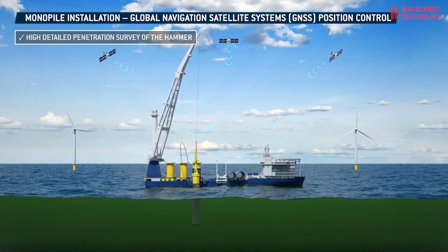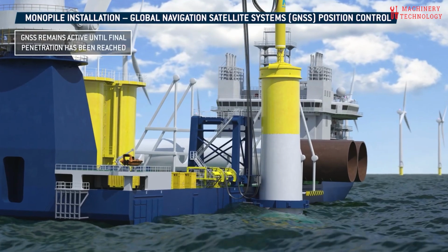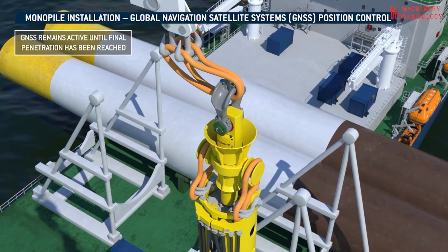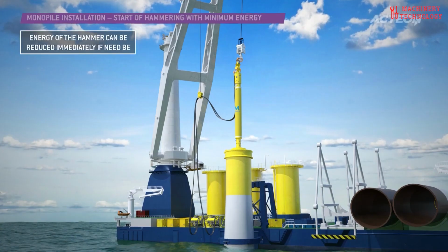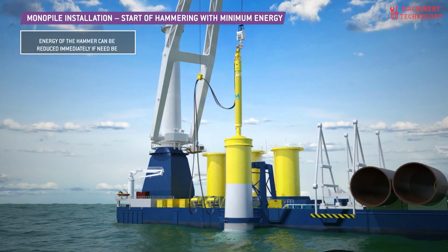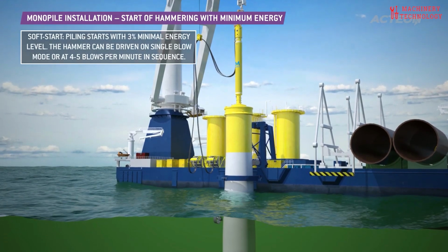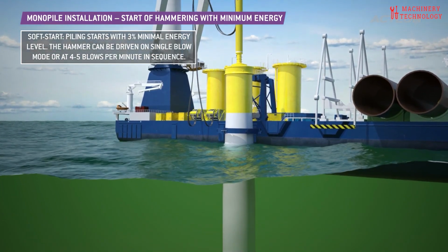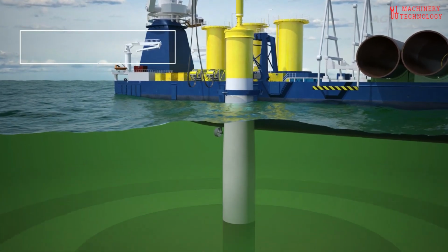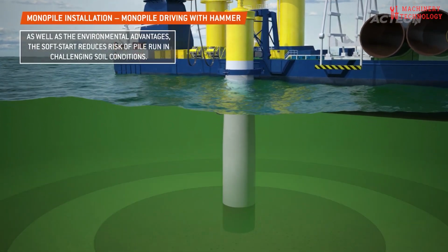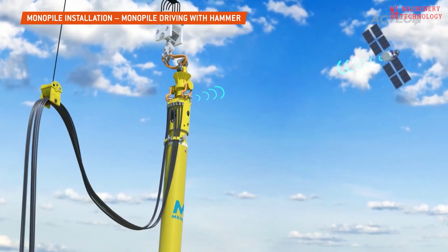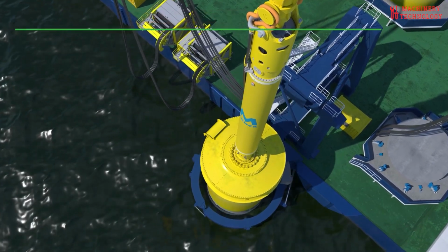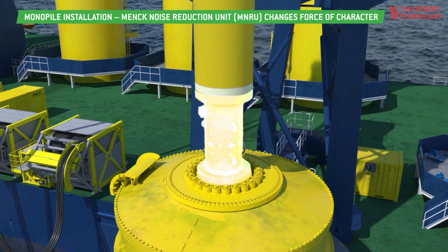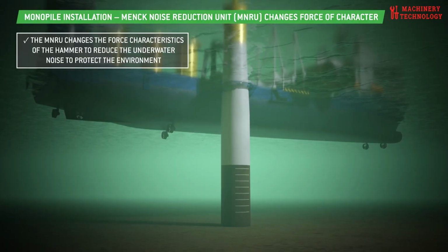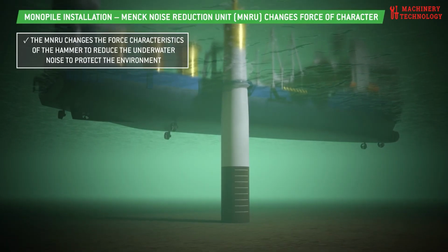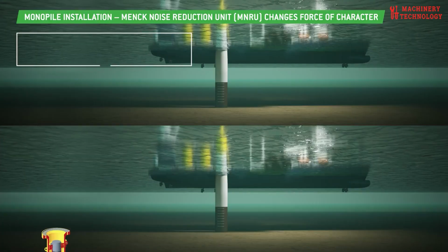Monopile foundations, widely used for their economic efficiency in shallow water offshore wind farms, have become the primary choice for fixed bottom installations. Each monopile consists of a single, large diameter structural element designed to bear the entire load of the above-surface wind turbine structure. Constructing a monopile foundation typically involves driving a massive hollow steel pile with a diameter of up to 4 meters and wall thickness of about 50 millimeters, approximately 25 meters into the seabed. The process includes penetrating a 0.5 meter layer of larger stone and gravel, which reduces the risk of erosion around the pile.